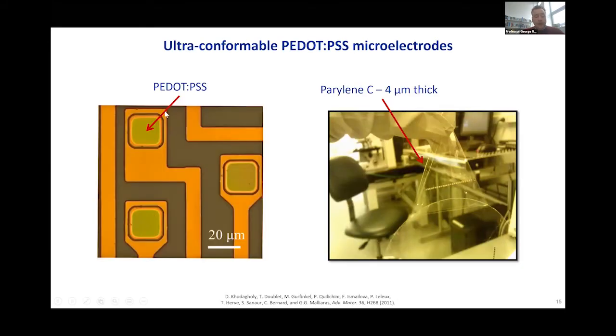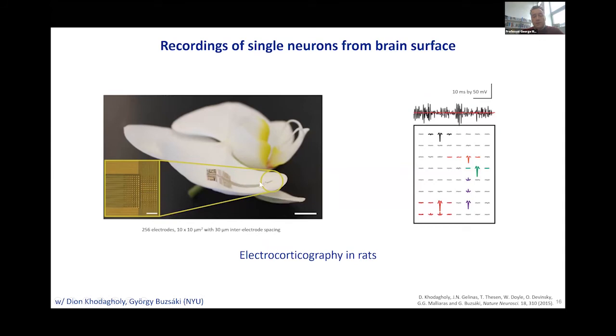This is shown here. We've made electrodes that have this coating, and these are microelectrodes that have the same size as a neuron, of the order of tens of microns. Now, without this coating, a gold electrode would not be able to capture the weak neural signals. You would need to make it much larger, and it will lose tremendously in spatial resolution. But with this coating, you can make it smaller, and now you can capture very fine signals from the surface of the brain. These have been integrated in very thin and flexible plastic membranes, so thin that they conform very nicely to topographies, such as the ones on the brain. Here they're shown on the surface of the leaf of an orchid. And the radii of curvature are compatible with the topography of the brain, including being able to get into sulci.